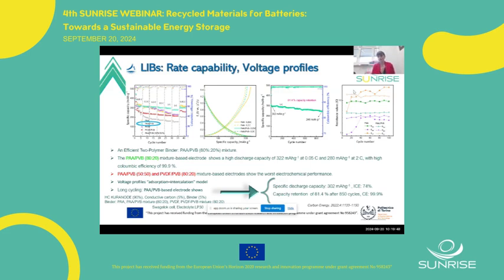The interfacial properties of the electrodes were also evaluated by impedance, and we understood that the PAA-PVB based electrode has a more stable interfacial behavior.